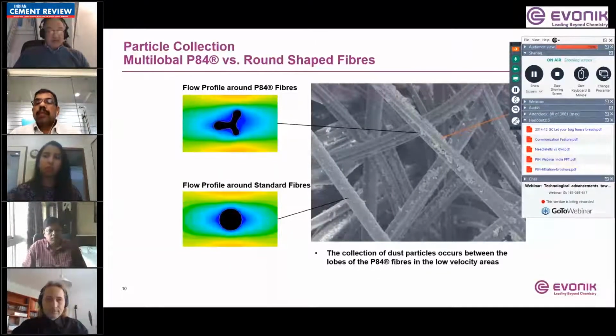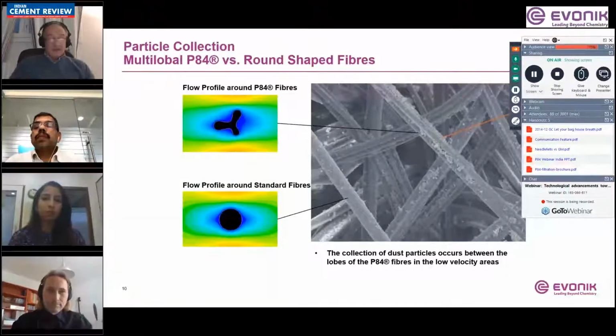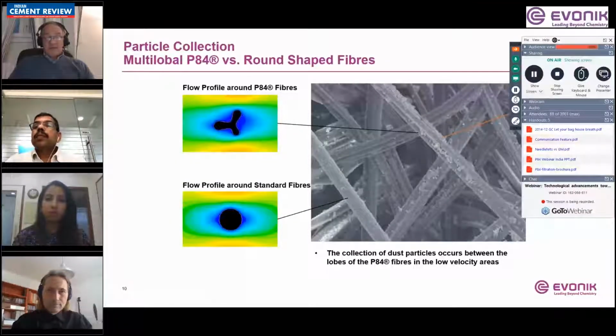These areas naturally capture and retain the dust, thus creating a permanent dust cake which protects the rest of the felt from dust penetration and dP increase. Instead, standard fibers, pictured on the bottom left image, which have the round cross-section like any other fiber in the market, do not really display this feature. And there is a lot of turbulence around them, so the gas does not allow for any dust capture, and the felt is more exposed to the fine dust penetration during operation.